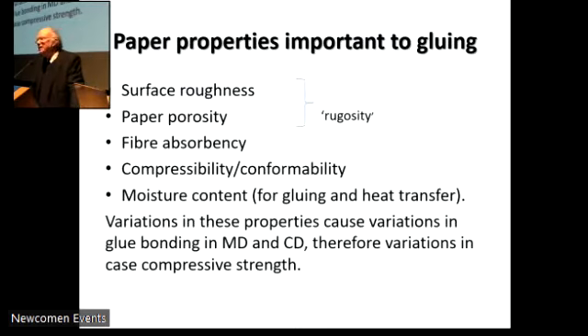Now, the glue itself is only one component of the gluing process. The other is the paper. And we're concerned with things like surface roughness and paper porosity, which sometimes are together known as the rugosity of the paper. Fibre absorbency is important because that governs the rapid take-up of moisture from the adhesive as it's setting. Compressibility and conformability of the paper are important through its thickness, what we call the Z direction, because that governs A, the amount of pressure that can be transmitted to the glue bond, and B, the actual area of the glue bond itself between the curved flute tip and the interior surface of the liner.